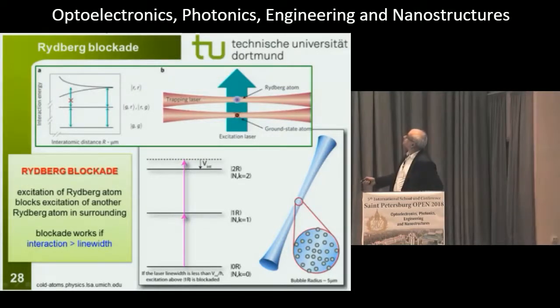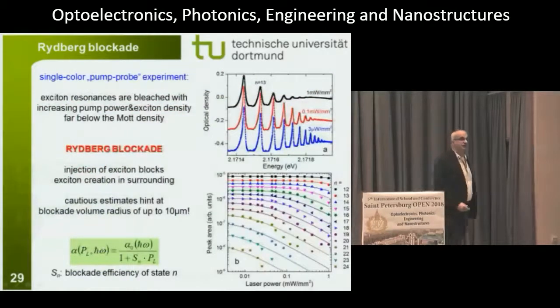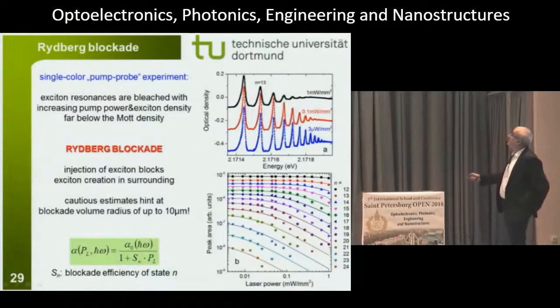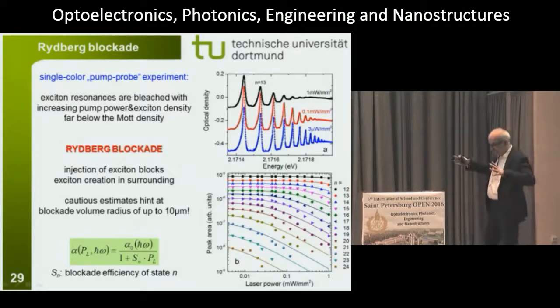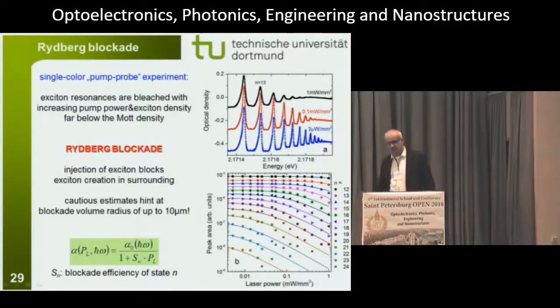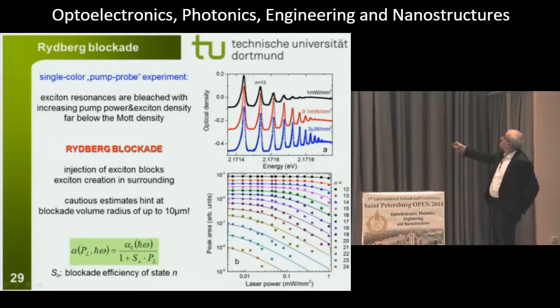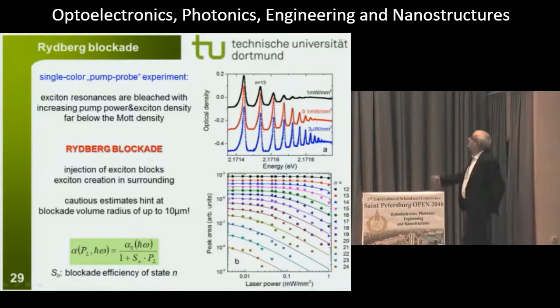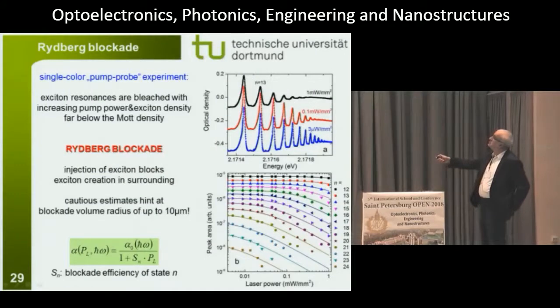So we were looking for the same thing, and we found indications for this already at the very beginning in our very first paper. When you look, for example, here at the absorption series, these are extremely low laser powers. We even increased the focus of the laser spot in order to reduce the laser powers into the nanowatt regime. If you increase the laser power slightly here, you see that the high energy lines are disappearing, while for the exciton lines on the low energy side, the energies remain stable and the line width does not broaden strongly. In fact, this is exactly the consequence of the Rydberg blockade.